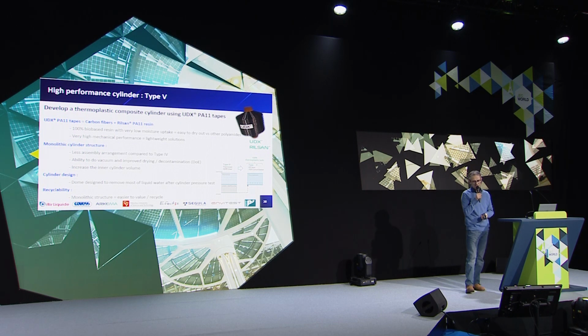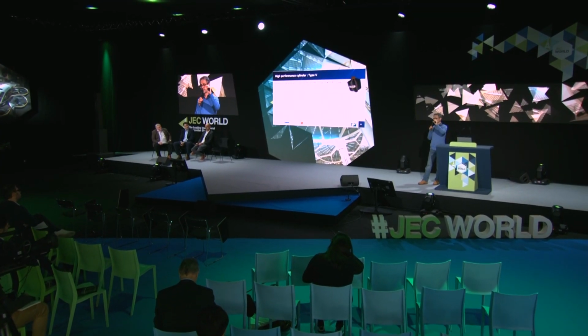And I call it monolithic structure. If you look at the sketch on the right, you can see that in a standard type 4 cylinder, you have a polyethylene liner with a composite epoxy structure, and that is not monolithic. There are two different materials. With the technology of Coves, they managed to have one layer made out of the same chemical, but on the first 2 or 3 millimeters of the inner part, which is the liner, you do not have any fiber. On the remaining thickness, you have roughly 60% of fibers in volume, but it makes one layer.